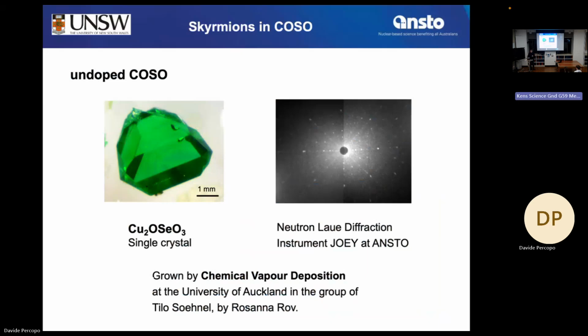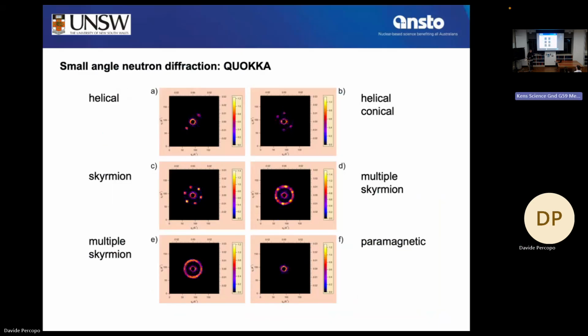We did neutron Laue diffraction at ANSTO to confirm the quality of the crystal. I'm not going into detail here, but you see this highly symmetric arrangement of these Bragg peaks. From that, we can determine the symmetry and the atomic distances. So that's what we see with small angle neutron scattering, and this is now entirely the magnetic signal.